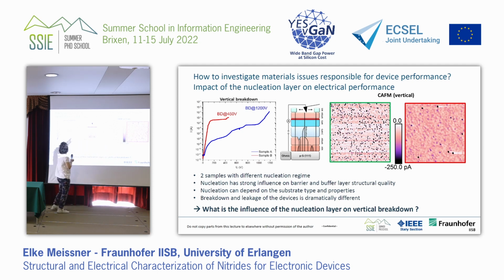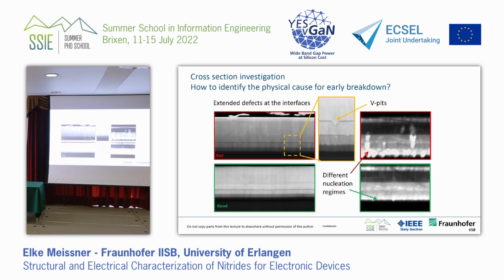And this material with many leakage spots is a 1200 volt material. So how come this? So you always have surprises. So what is the influence of the nucleation layer in this case? Why does it determine early breakdown? And what we found is, now we go to cross-section analysis. And we see the interfaces. And we have V-pits. But are the V-pits relevant or not?